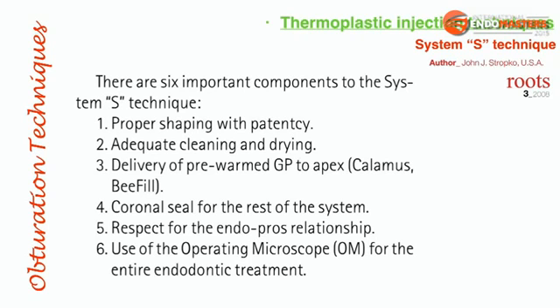So about the shaping and patency, we should say that the apical terminus of the canal should be kept as small as practical, and patency must be maintained during the whole procedure. Irrigation is used between each instrument during the entire shaping process, and patency is continually checked with a 10 file. Note that the volume of irrigants is probably the most important of things. Delivery methods that augment the volume of irrigant flowing to the whole length of the canals should be considered. One good example of this type of system is negative pressure irrigation with the EndoVac that guarantees at least 3 millimeters of irrigant within the working length.